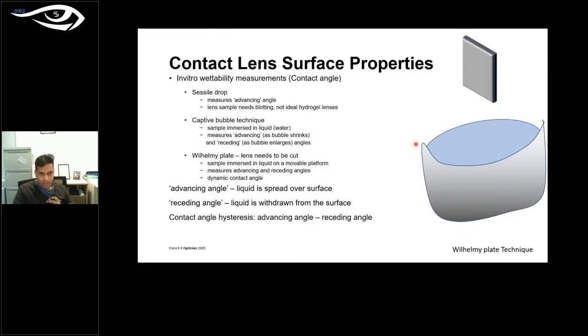So how is wettability measured? There are different ways of measuring wettability. We have the Sessile drop technique, the captive bubble technique, and the Wilhelmy technique. In the Sessile drop technique, as I mentioned in the previous slide, we just place a drop on the lens surface and then measure the angle. The type of angle that is measured is called the advancing angle. I'll come back to what advancing and receding angles are in a moment. In the captive bubble technique, rather than placing a droplet of fluid, we use a lens which is immersed into a liquid, often water. And in this, we measure both advancing and receding angles.